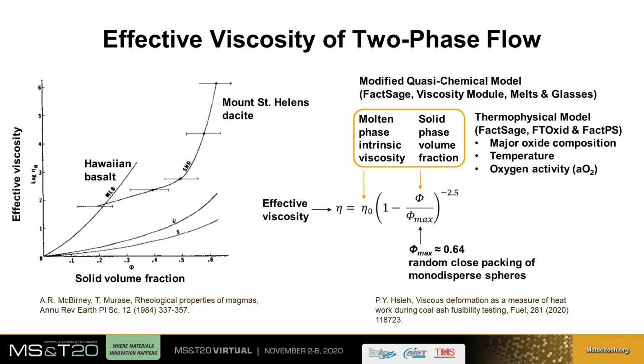Using FactSage thermophysical modeling software, it is possible to predict the solid phase volume fraction present in a two-phase system given the major oxide composition, temperature, and oxygen activity. The intrinsic viscosity may then be estimated using the modified quasi-chemical model based on the composition of the molten phase, also from thermophysical modeling, and the temperature. This approach to modeling the effective viscosity of subliquidus molten silicates helps to answer a very old question in ceramic engineering. How do pyrometric cones actually work?